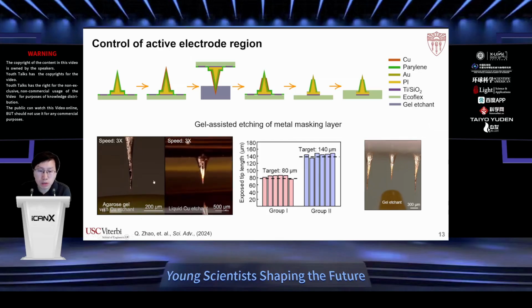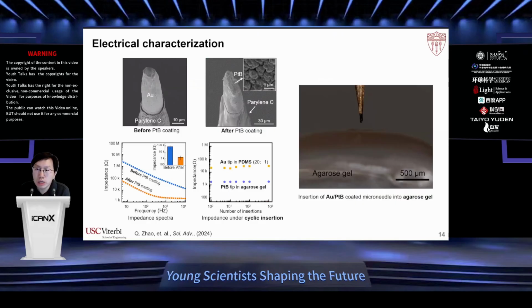so that when we dip the tip of the needle into the gel, we only etch the copper at the tip because of the large viscous force inside the gel. So this allows us to expose the tip of the microneedle with good accuracy. And we also coated the gold-coated microneedle tip with nanoporous platinum black, which can reduce the impedance by a few orders of magnitude, making it more suitable for electrophysiological recording.